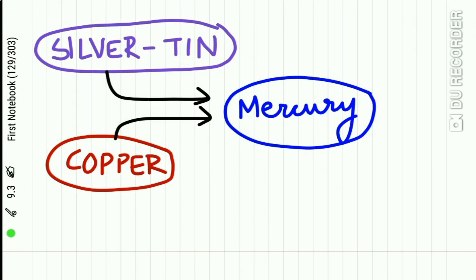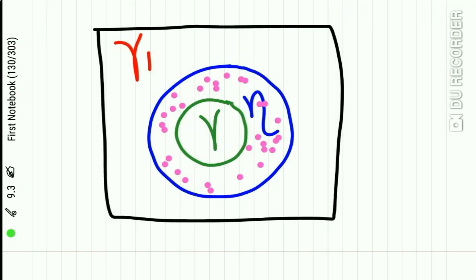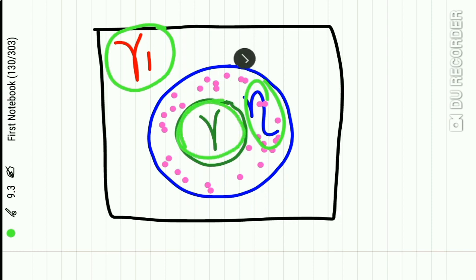As the name indicates, single composition alloys contain only one type of alloy particles — spherical particles of 5–40 micrometer size. In the setting reaction, silver and tin dissolve into mercury; very little copper dissolves. The resulting reaction gives a gamma 1 phase and the eta phase forms around the unreacted alloy particles. The microstructure shows a matrix of the gamma 1 phase and unreacted alloy particles surrounded by the copper-tin phase (eta phase).